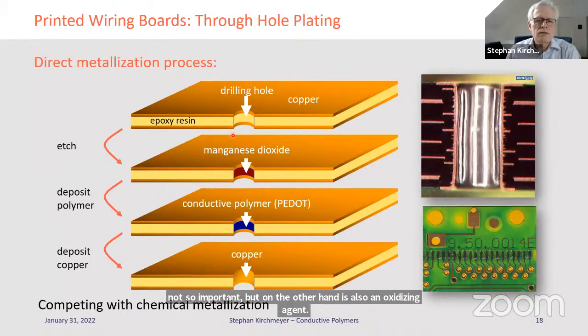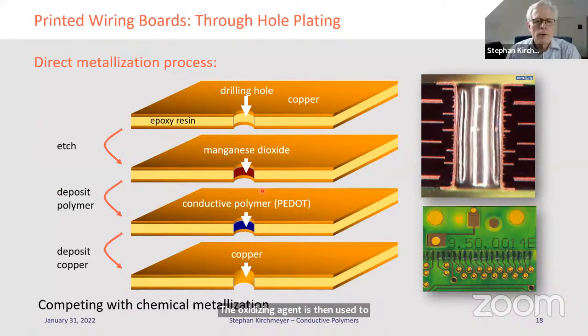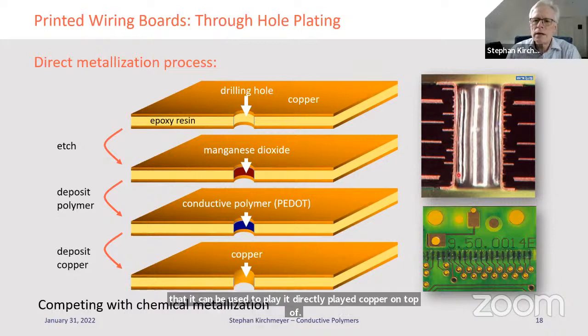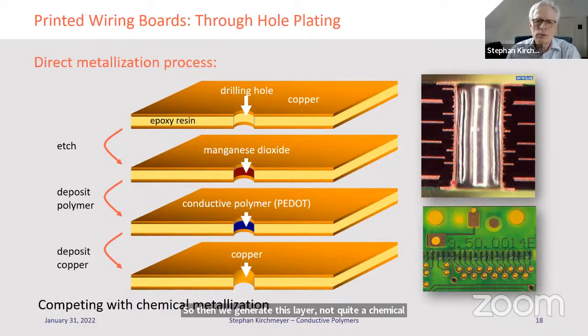The oxidizing agent is then used together with the PEDOT monomer to polymerize PEDOT on top of the epoxy resin. So there's a small blue layer now inside the hole, and this blue layer is sufficiently conductive that it can be used to directly plate copper on top of it. So then we generate this layer not by a chemical metallization, but by an electrochemical metallization. And this was, let's say, the motivation to get this into the technology and to use this instead of the palladium.